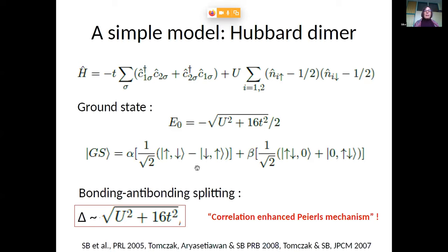It's actually a very simple exercise, where you have, as a function of t over U, coefficients alpha here, which determine how far or how close the ground state of this Hubbard dimer is to what we would like to call the Hund-Mulliken state, that means just the Slater determinant in a non-interacting system, or to the Heitler-London state, where you would have projected out double occupancies. So here you have two electrons on one vanadium and nothing on the other, or the inverse. And that state is, of course, possible if you are in a Hund-Mulliken picture, but it is projected out when you go to the strong coupling limit in the Heitler-London sense.